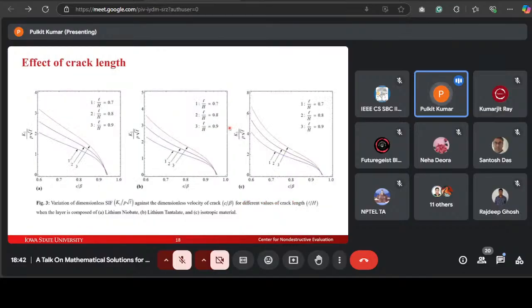Now for the crack length, this figure shows the effect of the crack length on the stress intensity factor. From the figures, we can see the crack length increases the stress intensity factor. This effect is observed in all three materials: lithium niobate, lithium tantalate, and the isotropic materials. As you can see here, the impact of the crack length on stress intensity factor is more significant in isotropic materials again as compared to the other two.